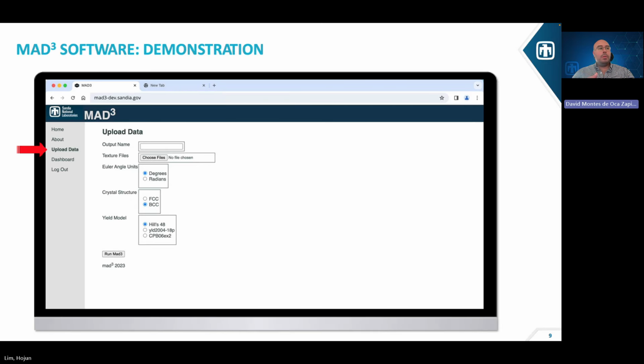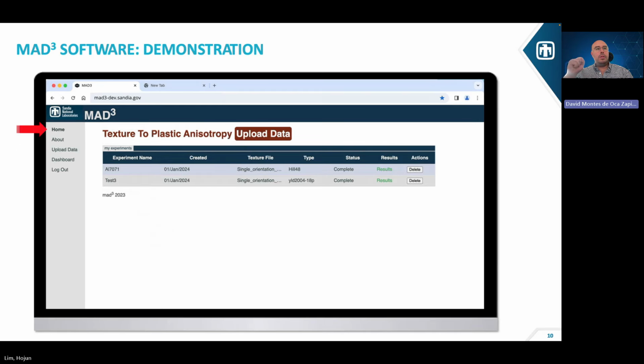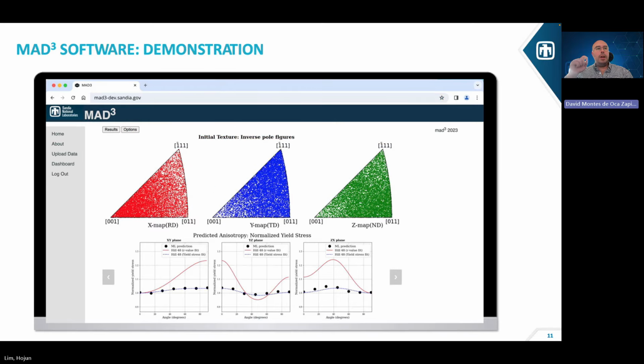With MAD³ you just simply click run MAD³, and in a couple of seconds, you get taken back to the homepage and the results now change from color to green. When you click on the results, that means that they become available. You are greeted with this page right here that shows you how ordered or disordered your underlying structure is from the data that you got. It also provides you with your normalized yield stresses. These are the directional strength that Hojun mentioned, and essentially you see that as the angle changes, those will change depending on the texture of your material.